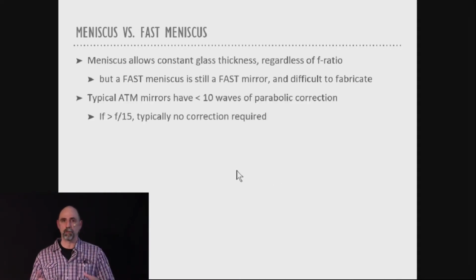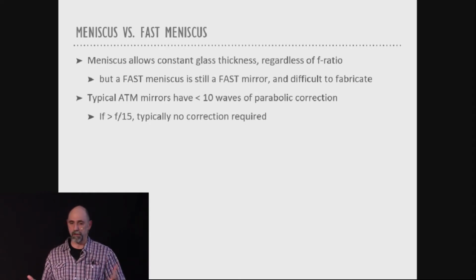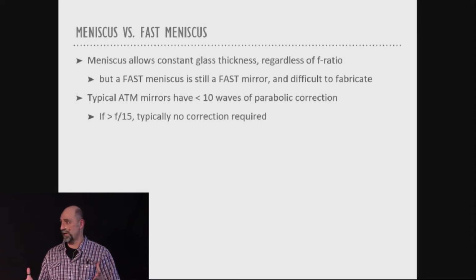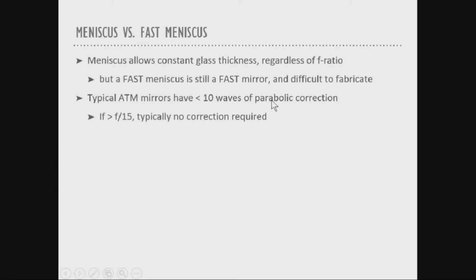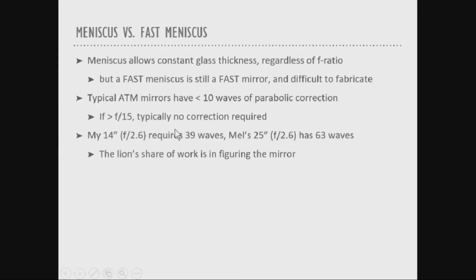Typically, when you're making a mirror on your own, you start by creating a spherical shape, and then you parabolize it. And the delta in going from the spherical mirror to the parabola is usually measured in the number of waves of light, waves of green light. Typically the correction that you have to put into a sphere to make it parabolic is usually less than 10 waves for a typical ATM mirror. And if you're over, say, F15, you typically just work with a spherical mirror. You don't put any correction in at all. My f2.6 requires 39 waves of correction, and the 25-inch of Mel Bartel's has 63 waves of correction.